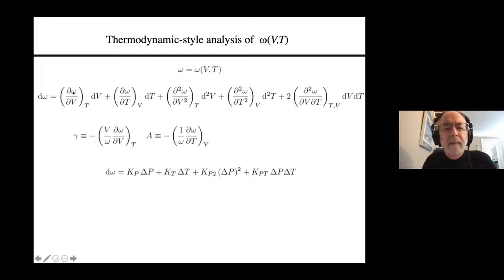Well, the fractional amount of that is the Grüneisen parameter. We're quite familiar with that. It's widely used, especially under pressure. The next term, though, is how the frequency changes with temperature at a fixed volume. So this is pure anharmonicity. We don't even need to have thermal expansion for effects like this to take place. And I'll call this an anharmonicity parameter defined in a similar way as the Grüneisen parameter.